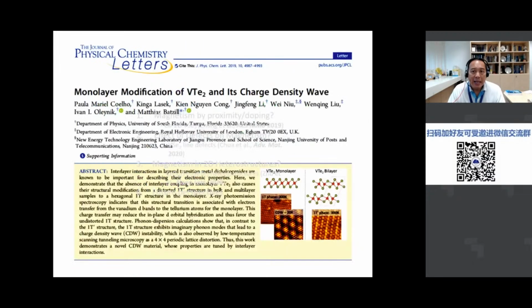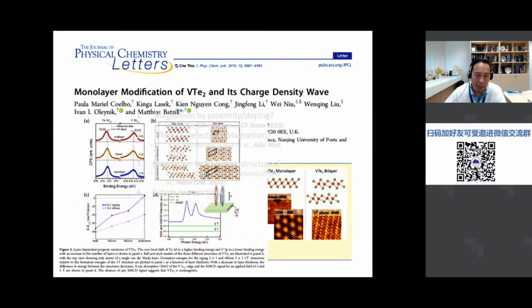And it turns out that later on, the same group, the Batzill group, reported in JPCL on vanadium ditelluride. And this time, in their paper, of course, they were talking about the charge density wave, but they did XMCD this time, and you can see the XMCD signal here. And they agreed that vanadium ditelluride is non-magnetic. So this time, the same group that reported magnetism in VSe2 did not see magnetism in VTe2.